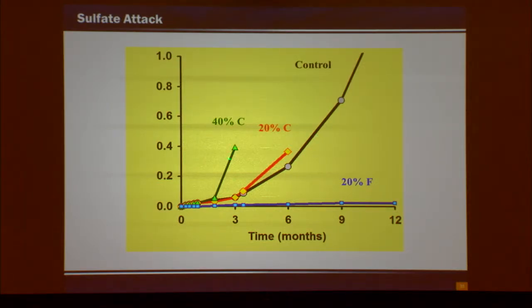Here's 40%. That didn't get better because the chemistry of the glass of the C ash is completely different than the chemistry of the glass of the F ash. So we kind of have to know these things. And if you read our specification, we say no C ash in sulfate environments. So why do we do that? This phenomenon right here, because the chemistry of the fly ash is not set up to control that durability mechanism.